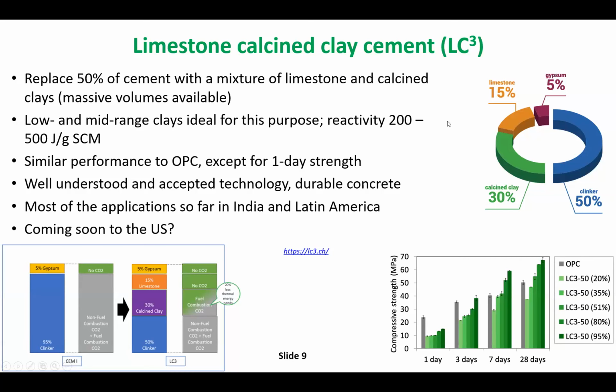And ultimately, for the most part, this technology makes concrete which performs almost exactly the same as normal Portland cement concrete. The major difference, as you can see on the graph on the right, is probably the one-day performance, where strength at 1 day actually does reduce. You almost pick it up already at 3 days. So yeah, there's a little bit of a concern with the 1-day strength. Almost everything else - there's hundreds of papers on this - they have shown that you get really nice durable concrete with such a technology.